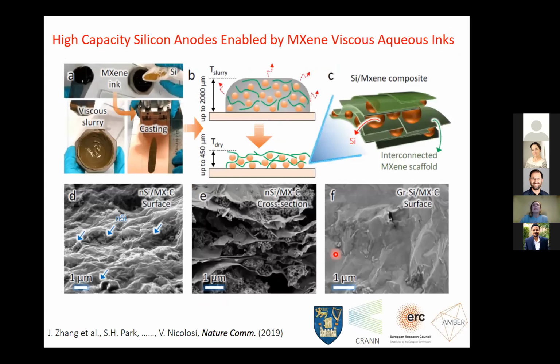So what we have done is we have added basically MXenes and made composites by simple slurry casting, which is the technique that the battery industry uses. We basically managed to make hybrid composites of silicon particles and MXenes by slurry casting. And what we have seen is that the MXenes were forming 2D sheets or blankets surrounding the silicon nanoparticles. And these really had two main advantages. One was giving mechanical robustness to the electrode. And the second one was that it really gave the conductivity that the electrode needed to function properly.